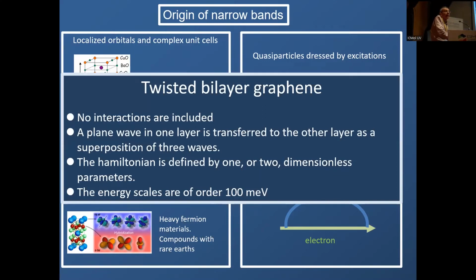But here, the interesting thing is that you neglect interactions in the calculations I have mentioned to you before. You just plug in parameters for non-interacting electrons in graphene, the smallest of which is about 100 meV. And out of the calculation, you get bands which have a width below 5 meV, which is still quite mysterious.